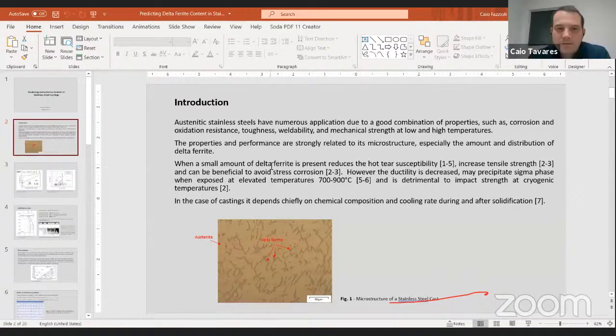What is the mechanism? Usually, the main issue is when we have a stainless steel that is 100% austenitic, with zero ferrite in the microstructure. The experience that I have in casting is that when you have zero ferrite in the microstructure, during the solidification it is very common to see hot tears. And also, when this kind of component requires welding, it is very common to happen. And why does this happen?